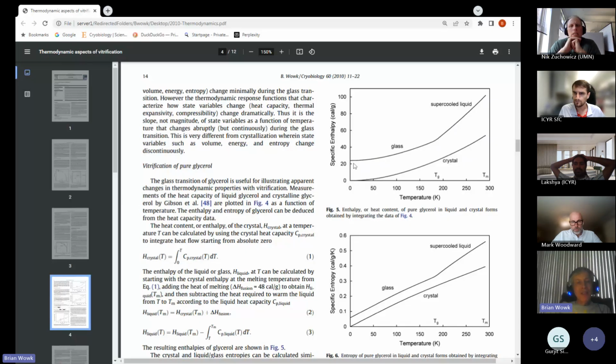No, what it reflects is that the molecules are basically farther away from each other in the, well, we've got to watch out for that because water expands when it freezes. The hydrogen bonds are weaker in the disordered liquid state than they are in the crystalline state. So in the crystalline state, the hydrogen bonds are in a deeper potential well. There are more oxygens and hydrogens that are closer to each other in tight hydrogen bonds in a crystal than in the disordered liquid.